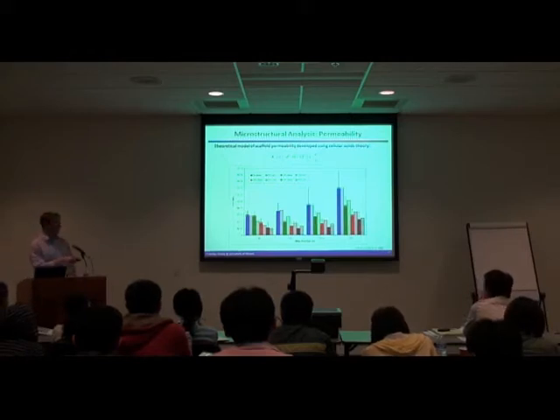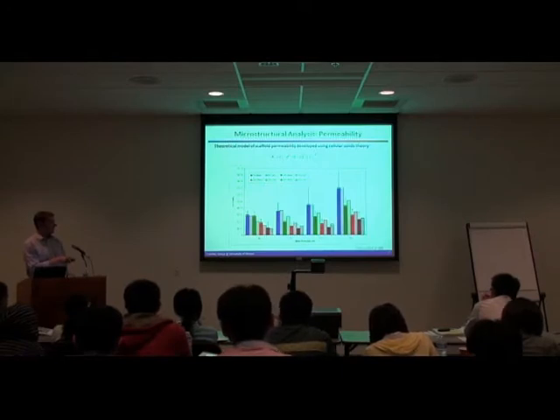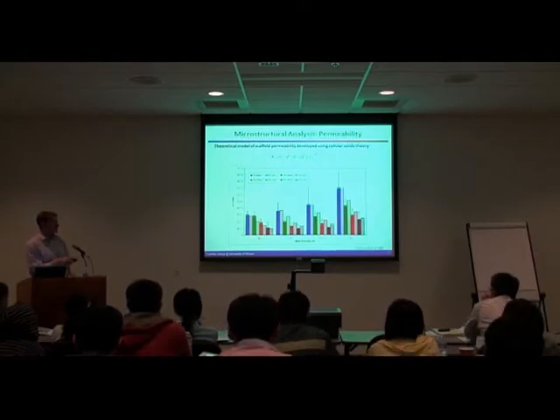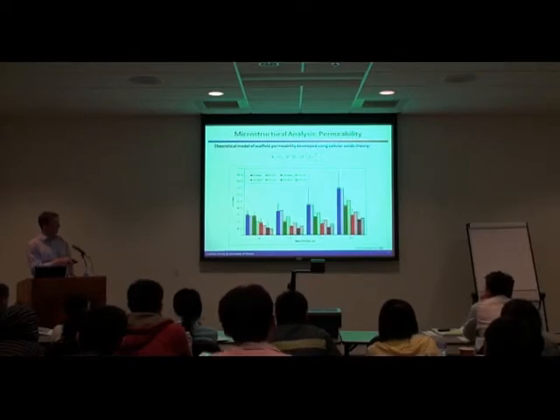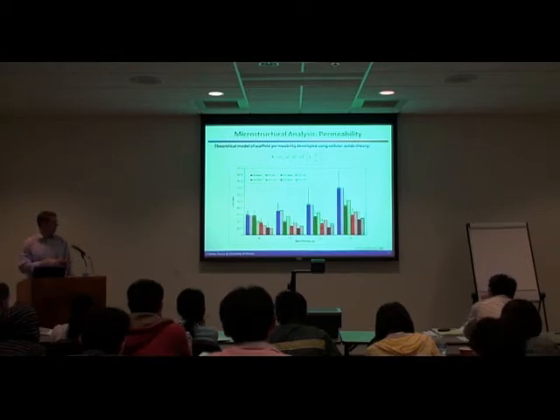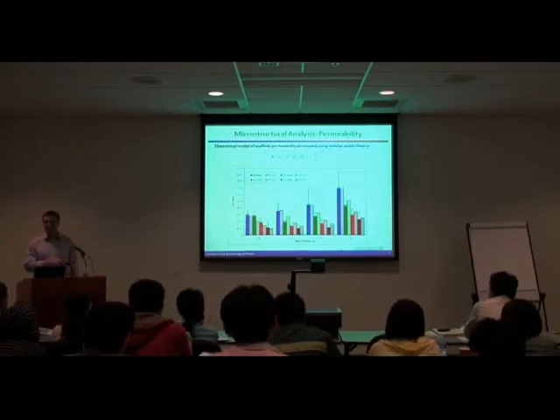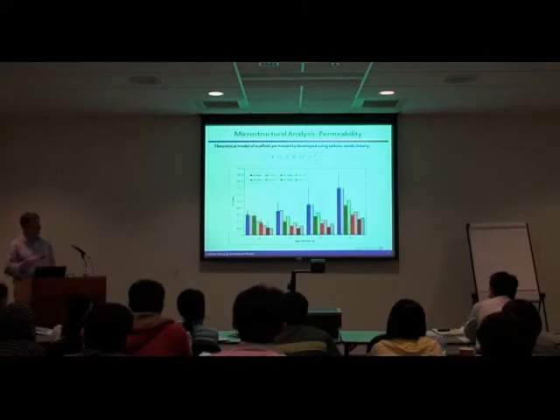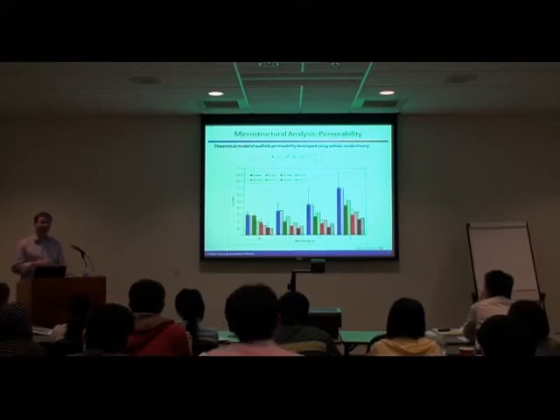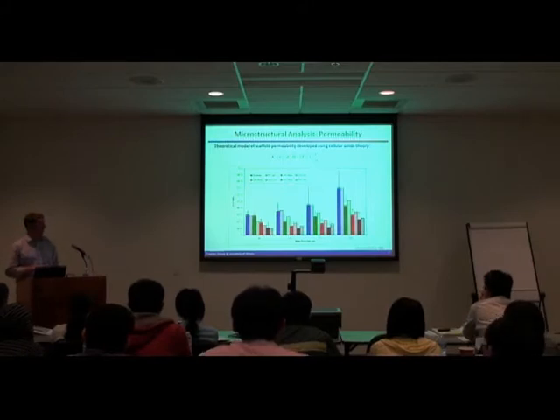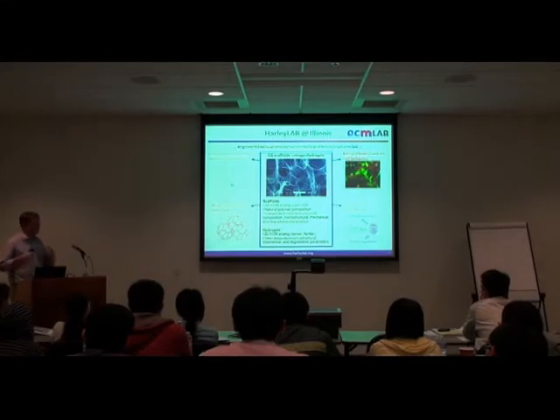And so what we have here is a rather complicated chart, but what you see is solid and striped bars. The solid bars are experimental measurements of the permeability of four of our scaffold variants with pore sizes between 95 and 150 microns under 0, 14, 28, and 42% strain. And then the striped bars are the model prediction that we have with one constant up front. So there's only one constant that describes the behavior of all these biomaterials together. What I'm trying to give you a sense of is that you don't have to just make a biomaterial, give a good guess at characterizing it, and move on. You can do a lot of really careful modeling and characterization work to give you a much better sense of the environment that you're creating. All right, so let's now start talking about using these materials.